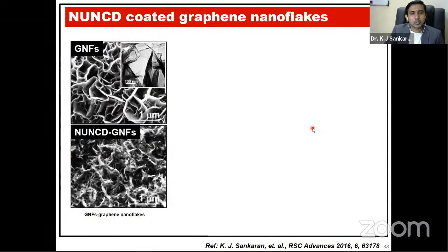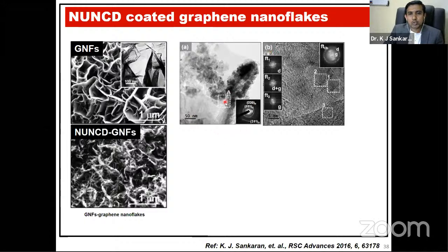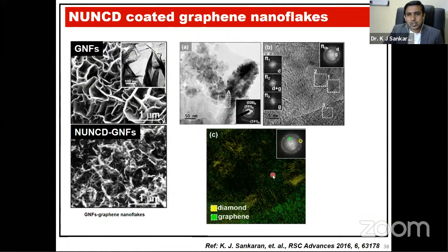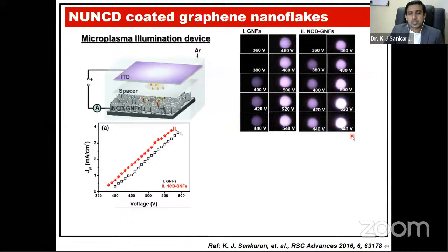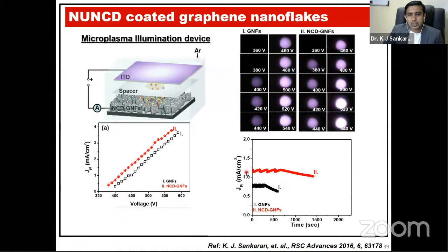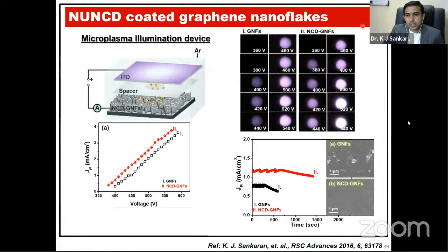We also tried to coat the NUNCD on graphene nanoflakes. This is the NUNCD coated on the graphene nanoflakes, and this TEM shows the diamond coated on the graphene nanoflakes. The colored high resolution image shows the graphene in the green region and the nano diamond particles, coated on the graphene nanoflakes, in the yellow region. That represents very good, stable electron emission at high voltage with high intensity, at 540 volt, compared to only the graphene nanoflakes. And you can see that the stability is really good, more than 1500 seconds, compared to the bare graphene nanoflakes. You can see that the graphene nanoflakes were completely etched out around 500 seconds.